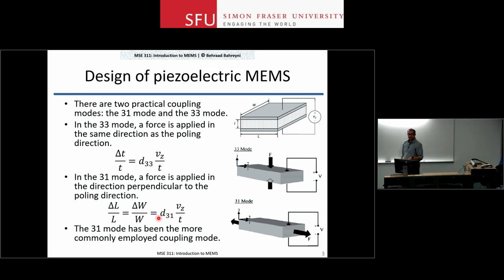Typically, the 3-1 mode is the one that we use more often. The simple reason is that the materials that we deposit and fabricate in MEMS, you stack on top of each other. So in most situations, the bottom electrode is at the bottom of this material stack, then you have the piezoelectric layer, and then the top electrode on top of that. So your field is almost always normal to the direction of the wafer. But in most situations, the displacements that you intend to get are in the plane of the wafer, and to do that, you have to utilize the 3-1 mode.